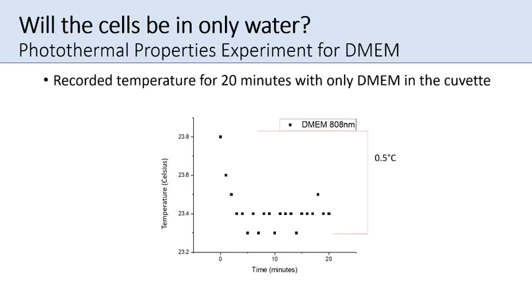What we actually see is a decrease of about 0.5 degrees Celsius. I think the reason is that the DMEM has to be warm to go into the cells, so it's sitting in the incubator, a lot warmer than the surrounding space. The photothermal experiment runs in a cold metal box that blocks off any light and heat, for safety reasons and to keep it more accurate. We go from a very warm temperature to a very cool one, so I think what you're seeing in this region is it just adjusting to the temperature of the box. After that, we don't see any real change, about 0.2 degrees Celsius variation for the rest of the time.